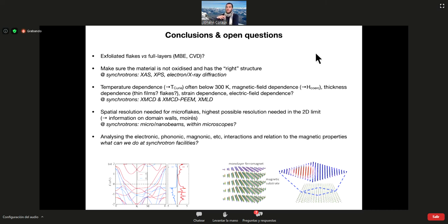But if we make this assumption and try to measure, which we've done, some hysteresis loop of the bulk compound, we already see that there is some in-plane anisotropy, but it's not sufficient to consider the dipolar energy to understand that, meaning that there is something else, and there is an intrinsic magnetocrystalline anisotropy, which we believe is out of plane. Okay, so there is a competition between two effects: the magnetocrystalline anisotropy pushing the magnetization out of plane, and the shape anisotropy pushing the magnetization in plane.